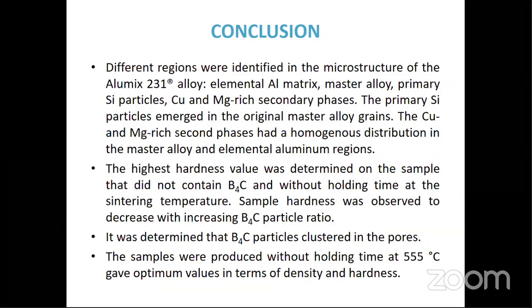Sample hardness was observed to decrease with increasing boron carbide particle ratio. It was determined that boron carbide particles clustered in the pores. The samples produced without holding time at 555 degrees gave optimum values in terms of density and hardness.